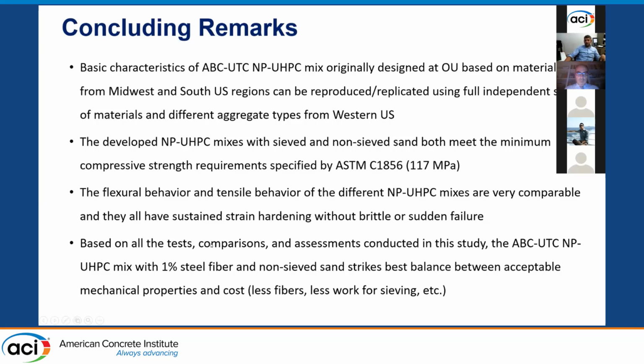So what we did as part of the ABC-UTC, and again, this is only for this project, we don't want to make bigger conclusions yet, but based on what we have seen in this recent collaboration among the ABC-UTC, we at UNR recommend that using 1% steel fiber and non-sieved sand would strike a balance between acceptable mechanical behavior and cost. Less work for sieving means less work, especially if you are scaling this up for large quantities. Less fiber, of course, will mean less cost. So there is room to engineer UHPC based on the application.